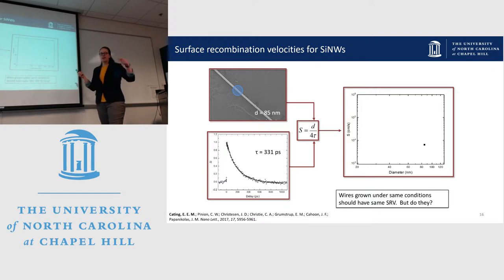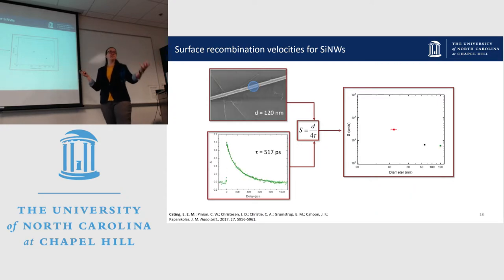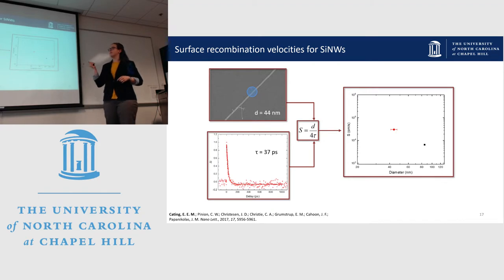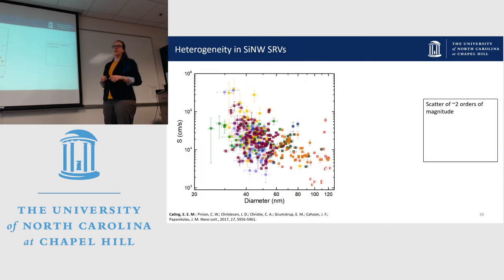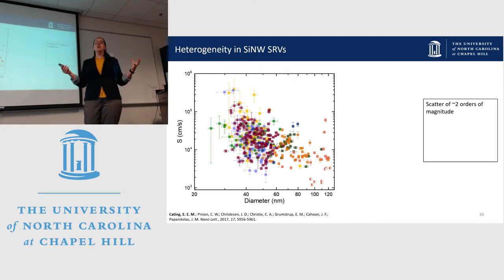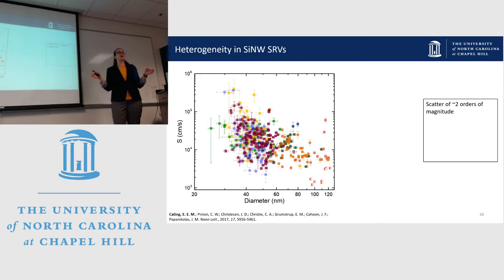So again, I wanted to see if wires grown at the same time would have the same value. So I did this again on a wire from the same growth batch, and again, and again, and 300 more times. And there's a lot going on in this plot, so I'm gonna break it down. The first thing that I want you to notice is the scatter that we see. So if all the surface recombination, all the surface qualities, I'm sorry, were the same, you would expect this to be a fairly flat line, right? But instead, we see two orders of magnitude of variation between the slowest and the fastest surface recombinations.